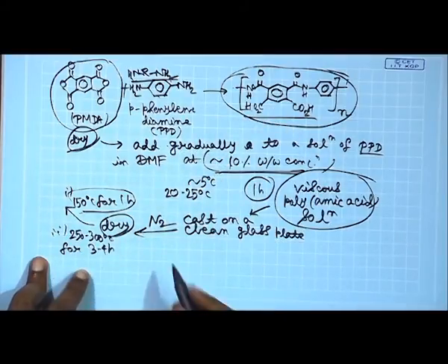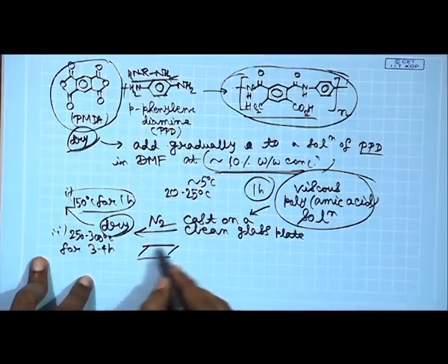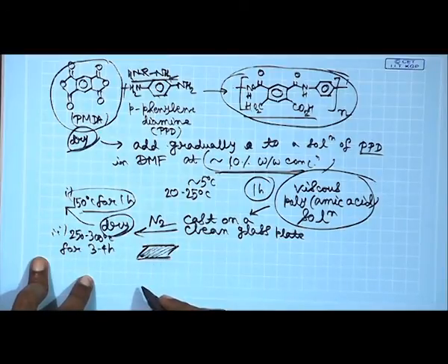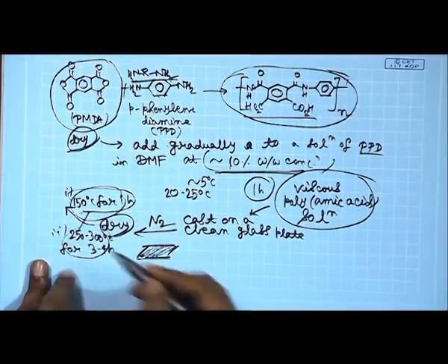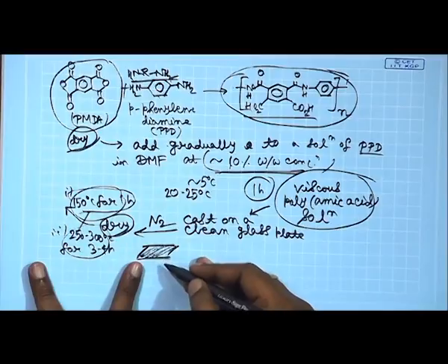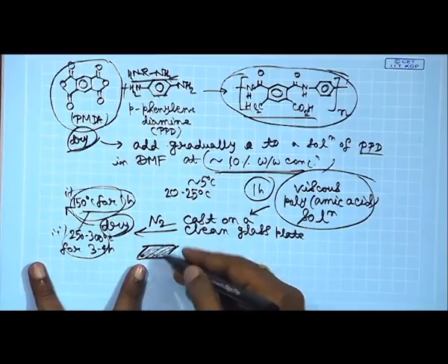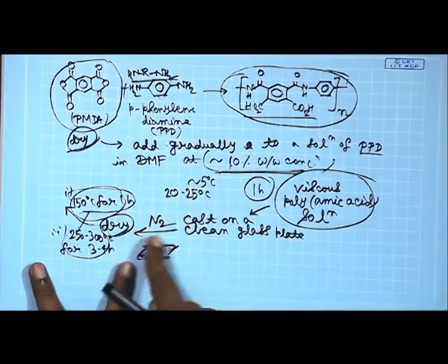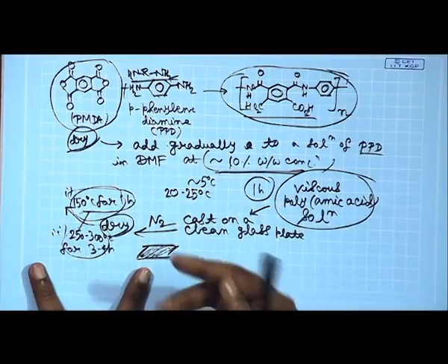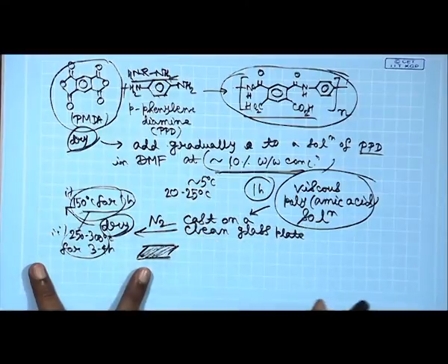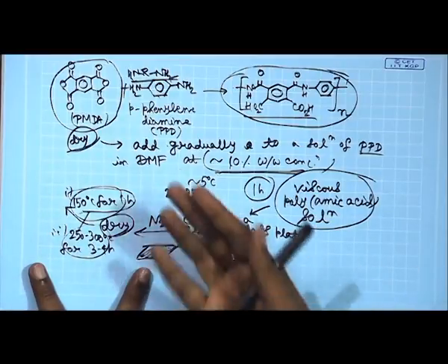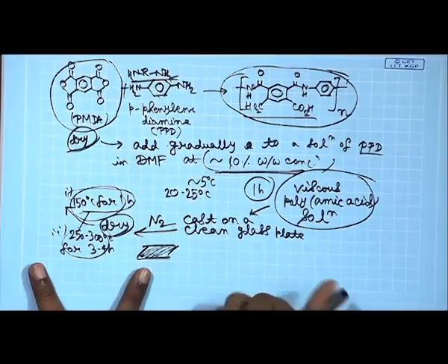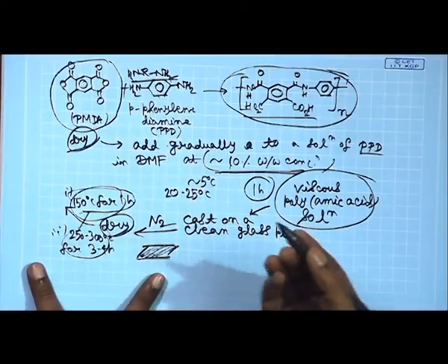That is the idea. So, what you have here then is your glass plate on which you have this film of polyimide. Now, you cool it down, because the process has been done at high temperature and cyclization has occurred. Then you immerse this glass plate in a water bath, and this film will just detach. Take out this film with a tweezer maybe, and then you dry it in air or heat it further and further.